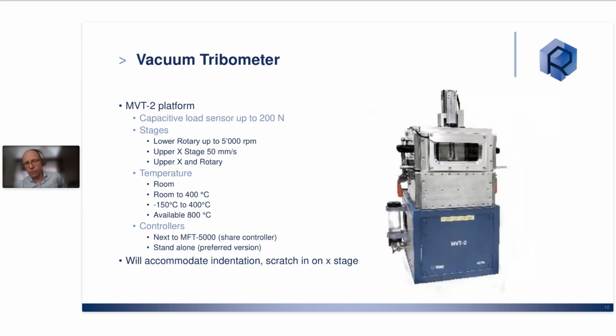And then, of course, for space application and other applications as well, the vacuum tribometer could be quite interesting. There are different coatings and lubricants that are very well known to have a very large difference of coefficient of friction depending on the level of vacuum. MoS2 was presented today, but there is also the DLC coating, which is very well known to have a tremendous variation of coefficient of friction if it's tested in air or in vacuum.